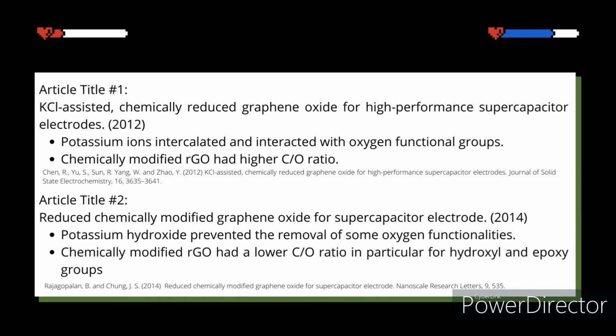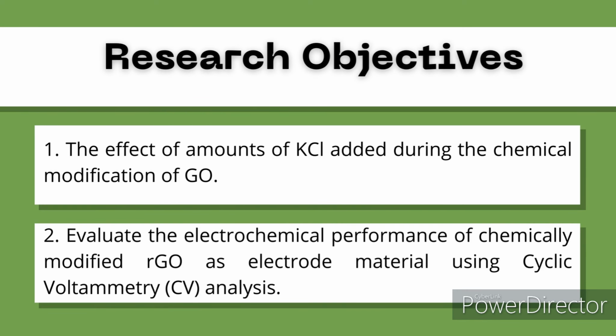Previously, Chen et al. studied the effect of KCl addition during chemical reduction of RGO for supercapacitor application. The authors found that KCl interacted with RGO and produced chemically modified RGO with a higher carbon to oxygen ratio. However, in another study, using potassium hydroxide to modify RGO, the authors found that the chemically modified RGO had a lower carbon to oxygen ratio and proposed that potassium ions can prevent the removal of oxygen functionalities. Hence, the research objectives for my work were to investigate the effect of the amount of KCl added toward the degree of oxidation in GO during the chemical modification step and evaluate its electrochemical performance as an electrode material using cyclic voltammetric analysis.